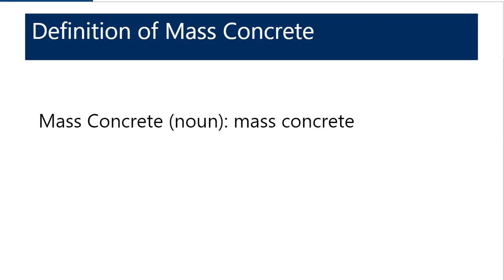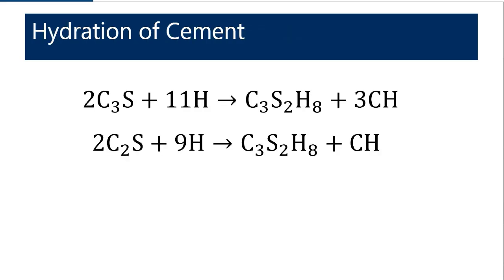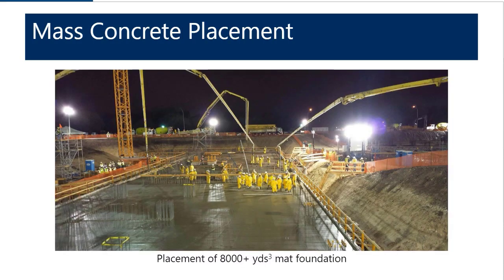So what is mass concrete? Well, how is this any different than maybe a concrete slab on ground that's 6 inches in thickness? And so what we need to remember is concrete is chemical. And so I don't necessarily want you folks to understand this chemical equation that's on the slide. But what I want you to understand is that the hydration of cement is an exothermic chemical reaction. If you take a little bit of water and a little bit of cement and put your hand over it after it's been mixed, you can actually feel the heat that's being generated. If you take a lot of cement and a lot of water, you can end up with a lot of heat. And that's what we're concerned about, is the amount of heat that's being generated.